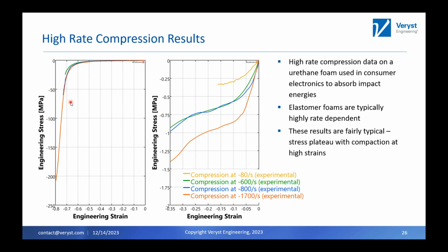I think that we did a urethane foam here. Whatever this urethane foam is made out of. And so really you're starting to get the compressive modulus of the urethane foam. And so it's just so much stiffer here, right? 200 MPa versus 0.5 MPa here at 4 or 5% strain. So